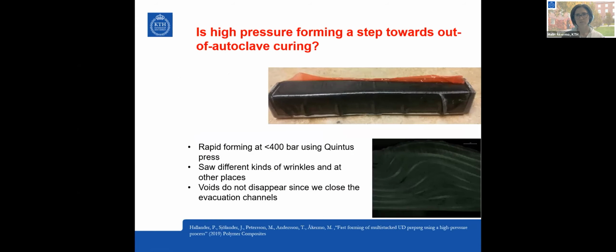So when we did understand a little bit more of how this worked, how the forming worked, why we got wrinkles, etc. When we did hot drape forming, we felt that, well, why can't we push this a little bit harder? I said before, you should find a processing window for your application, your automation process. So we started looking into whether there was a possibility to, instead of having the hot drape former, use a Quintus press, which is very similar, but instead of evacuating the air, you are actually using oil to press the membrane down towards the tool. So it goes very fast and you get a really high pressure.